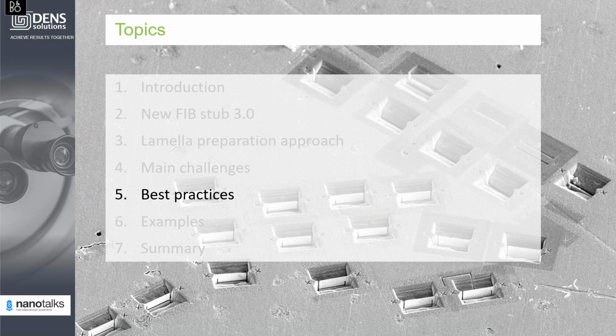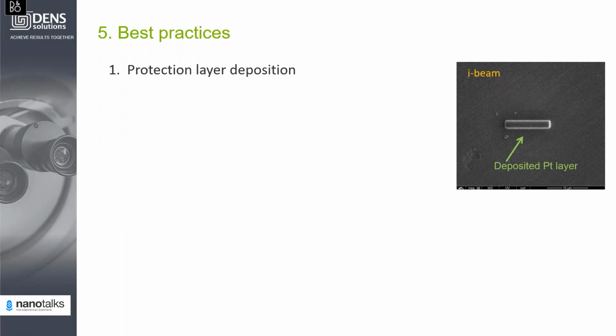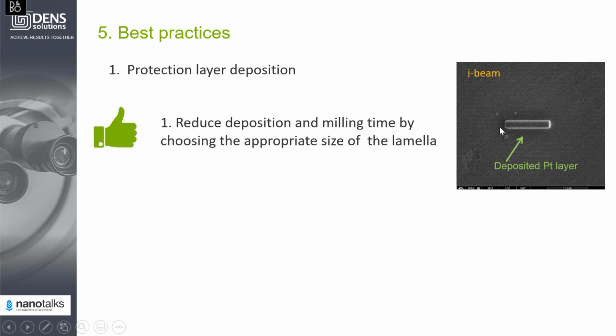So, moving to best practices. Basically, the idea here is to show a few examples of how to overcome challenges and improve the process. First of all is the deposition layer. The first suggestion is that you need to define the deposition layer to a specific, appropriate size for your experiment. The lamella should not be too small, so that it fits in the window. It also should not be too large, so as not to spend additional time on milling and deposition.